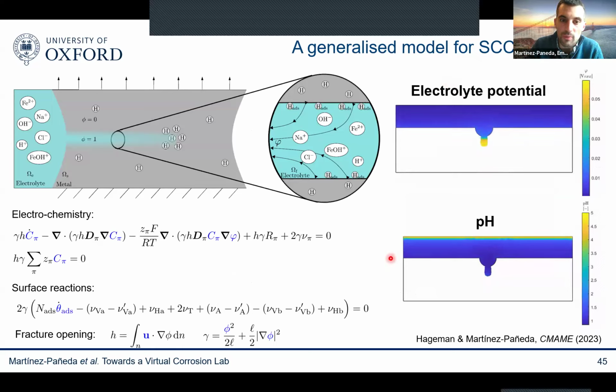And there are a few items, of course, that one has to take into consideration. The first thing is that you need to be able to capture well what is the crack opening. So there's some ongoing discussion in the phase field fracture literature and various approaches to capture the crack opening appropriately. This is something that people working in hydraulic fracture are very interested in, but it's also relevant here. We need to understand well the electrochemical behavior inside of cracks, and we propose a solution that you can check in our recent CMAME paper.